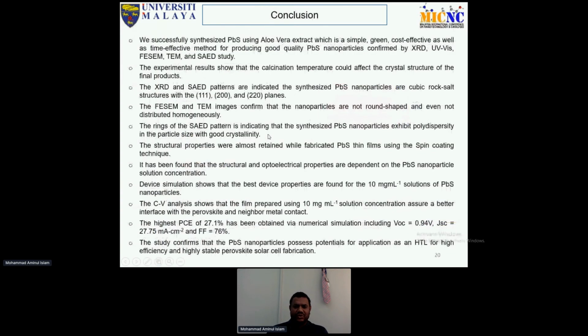So here is the conclusion. We get a high efficiency of 27.1% with VOC of 0.94 volt, short circuit current of 27.75 milliampere per square centimeter and fill factor of 76%. The study confirmed that lead sulfide has potential for application as an HTL for high efficiency and highly stable solar cell fabrication. Okay, thank you.